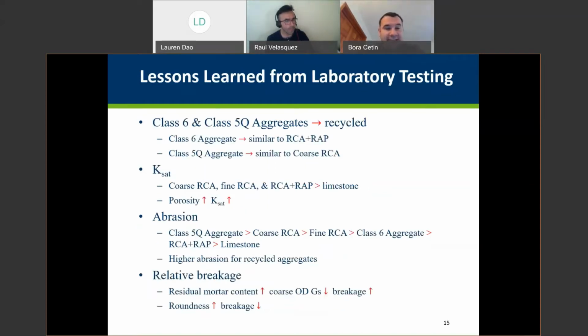So again, like I discussed with the pictures on the slides that we have of these materials, Class 6 and Class 5 aggregates, basically recycled base aggregates 2 and Class 6 aggregate, were more similar to the RCA RAP. It had a high RAP content, binder content. Class 5 aggregate was very similar to coarse RCA in terms of gradation and mortar content. When we look at the hydraulic conductivity of these RCAs, there is sometimes concern about their permeability, but both in the field measurements and in the laboratory measurements, the hydraulic conductivity, KSAT, of these materials was higher than limestone.